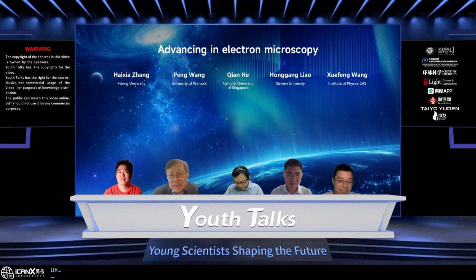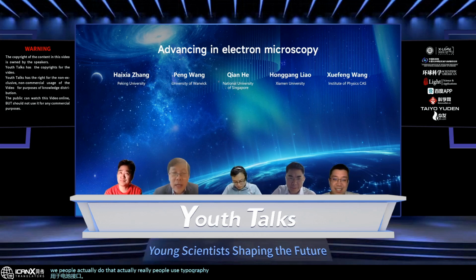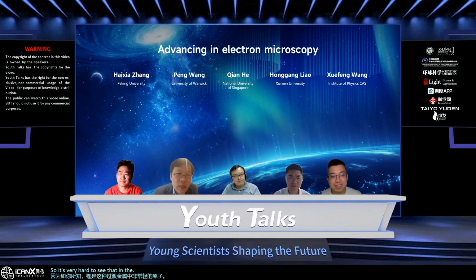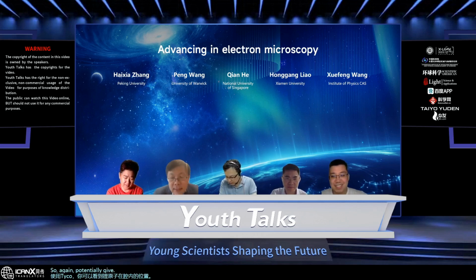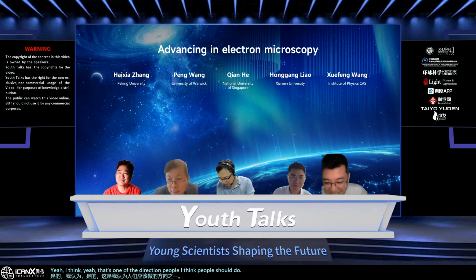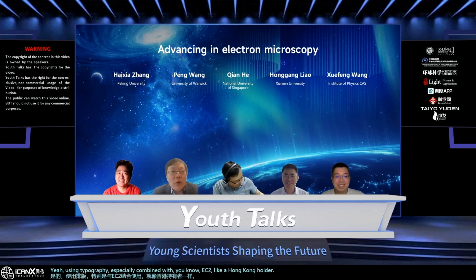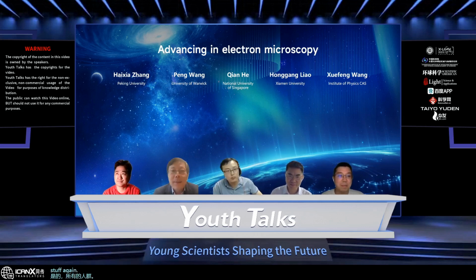So did you apply or try this method for the battery interface? People actually do that. People use ptychography to image lithium batteries, because as you know, lithium is a very light atom within the transition metals, so it's very hard to see in the HAADF image. Therefore, if you use ptycho, you're able to see where the lithium atoms are within the cathode, so it potentially gives a lot more information. I think that's one direction people should pursue, using ptychography especially combined with in situ holders, or cryogenic holders as well.